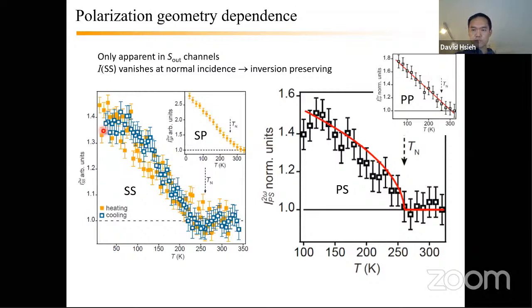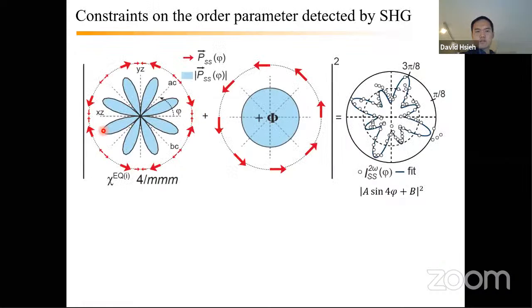So first let me talk about how one might just phenomenologically fit this data. At high temperatures, you have, again, an electric quadrupole I-type tensor respecting 4/mmm tetragonal symmetry. And in the SS channel, that gives rise to a pattern that looks like this.